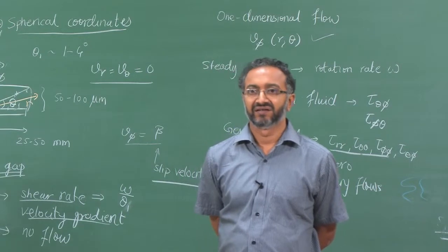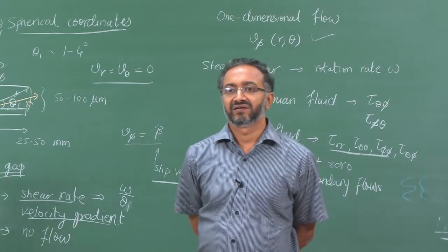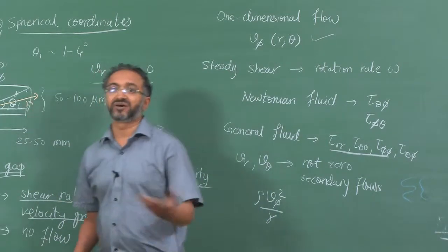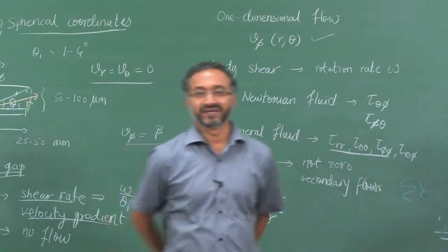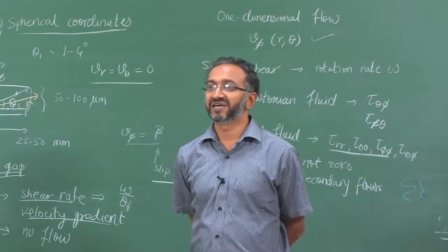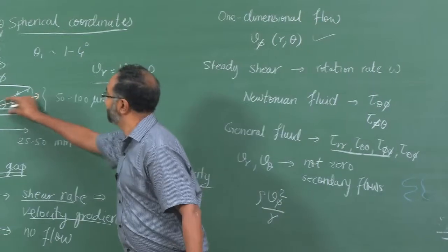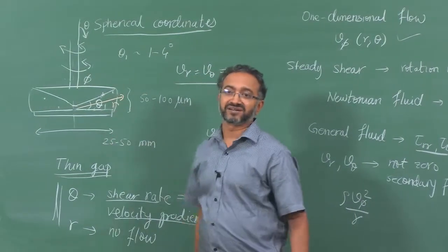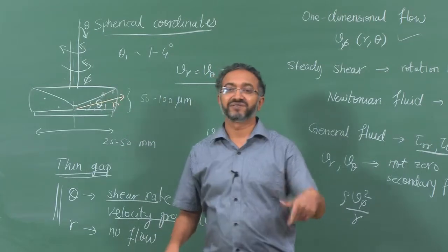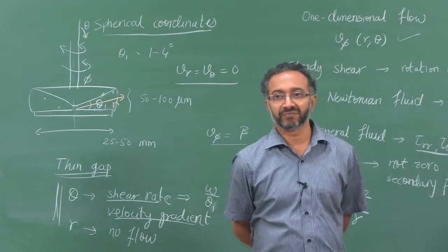So as soon as we reach the parallel plate, the uniform shear assumption will no longer be valid again. So a finite angle has to be there for us to make sure that the gap increases. But if we make too much of a gap, then other features may start playing a role.